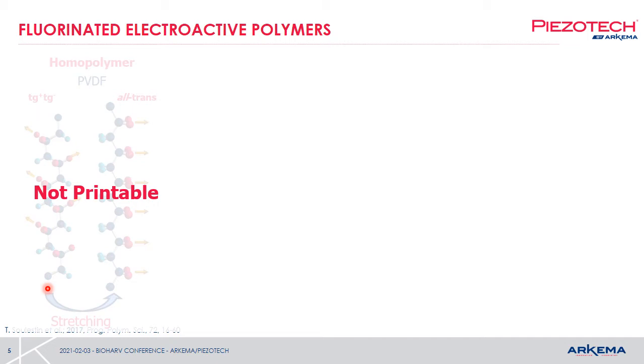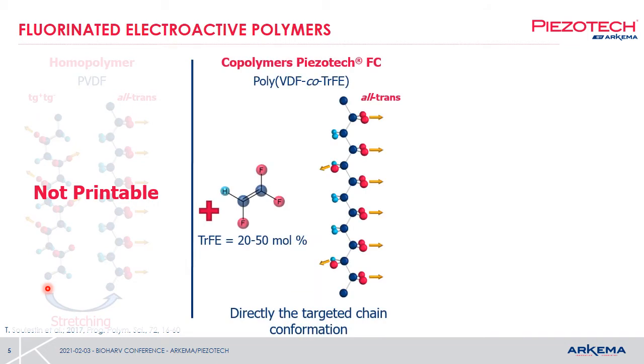So in the 80s, a new product was discovered: the copolymers of VDF and trifluoroethylene. If you introduce between 20 to 50% of trifluoroethylene, the additional fluorine atom of trifluoroethylene will induce an electrostatic repulsion between this CHF unit and the CF2 adjacent unit of both VDF or trifluoroethylene, and you will have, directly from the melt or from solution, the all-trans conformation. So directly the good crystalline phase that will be able to give piezoelectric properties.